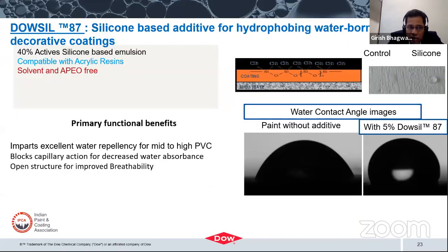And this is Dowsil additive 87, especially to impart excellent hydrophobicity, which is long term, even after exterior exposure. It's a 40% active silicone emulsion, and it's been recently approved at a few large companies. They're using it successfully to impart excellent water repellency for mid to high PVC.